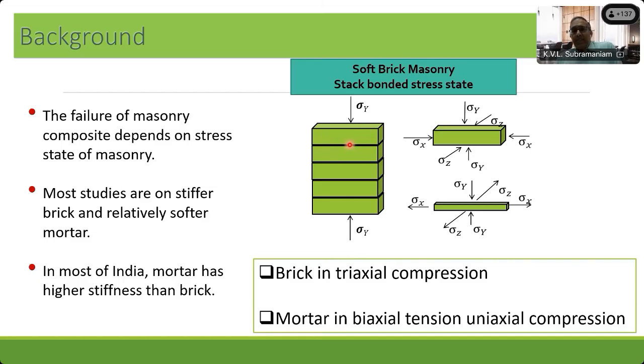When you apply a compressive stress, and remember what I'm applying is a uniaxial compression, if you look at the stress state in the brick, you have, of course, the vertical compression, which is the sigma y in the brick, but then lateral stresses also develop. Lateral stresses are stresses in the direction perpendicular to the applied compressive stress. And these stresses are developing in the brick. Similarly, stresses also develop in the mortar. So this is the mortar. You see the vertical stress here, but you also have these lateral stresses that have developed.